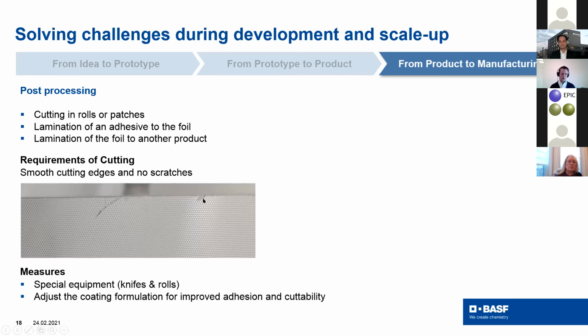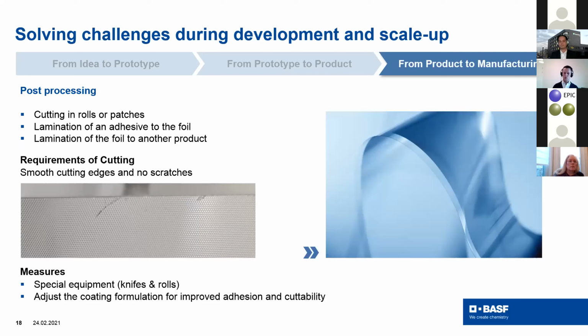And then you talk with your partner. He uses some special equipment like knives and rolls, and that diminishes the problem, but the problem is still there. And then you need to go back 2-3 steps, really change something. For example, here we changed the coating formulation for improved adhesion and cuttability. In the end, we really came to a nicely cut foil with no defects over all the rolls we produced. And then you really can start to scale up.